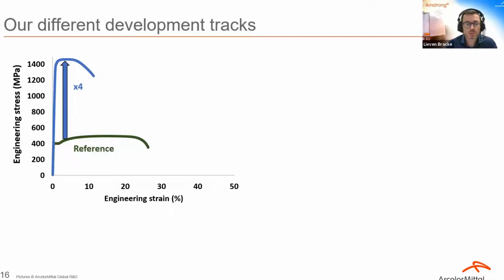These steels go up to a yield strength of about 1500 MPa with still good bendability and toughness. And these steels are also suitable for wear and abrasion applications. And if I may, I can also indicate here a kind of short reply to one I've seen in the Q&A from Mr. Vazouras. So that the high strength reduces the ductility and elongation of these steels, which is true to a certain extent. We cannot deny that, but as you can also see, we can find solutions where we can triple, quadruple the strength, and the ductility is still at a very acceptable level of 10, 12, or even 15%. So it's with new metallurgical tricks we can circumvent the conventional issues to a certain extent.